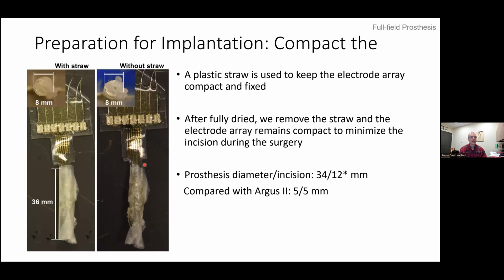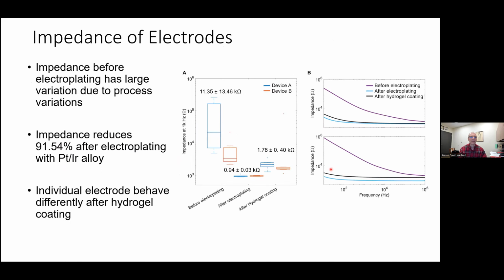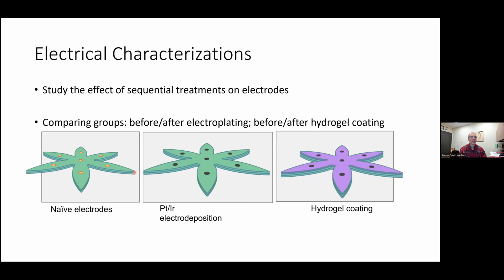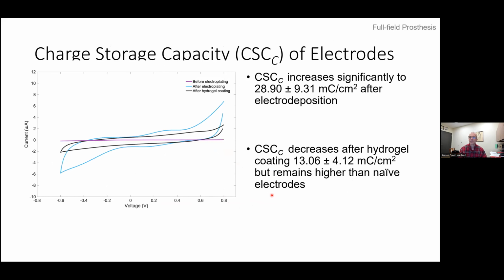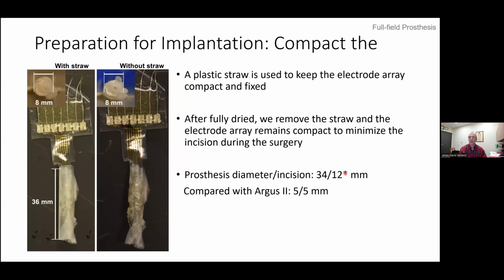And we think if we really pushed forward just to demonstrate this approach, by optimizing the mechanical design, by optimizing the folding strategy we use, we can reduce this significantly, perhaps even by half. So we show you here a 34 millimeter wide electrode, and what does that mean? That means from this tip to this tip, it's 34 millimeters. We were able to get this through a 12 millimeter sclerotomy in the eye, which is still too large if you ask surgeons.